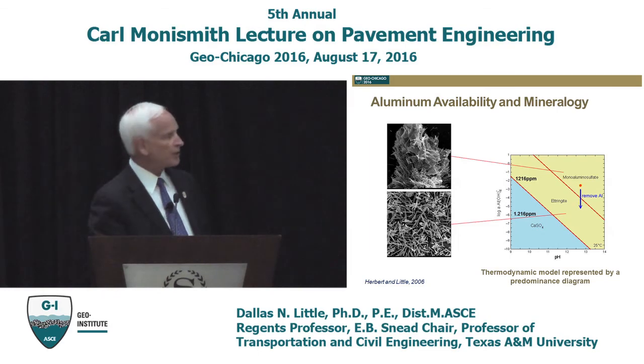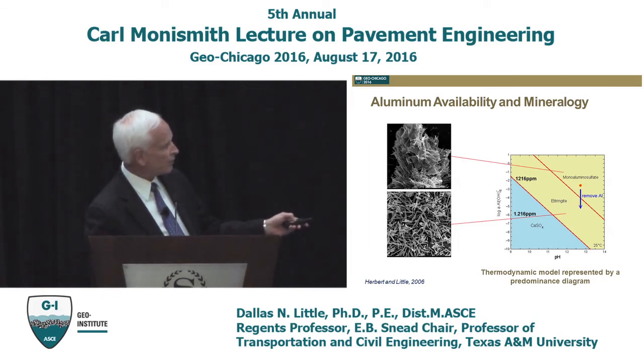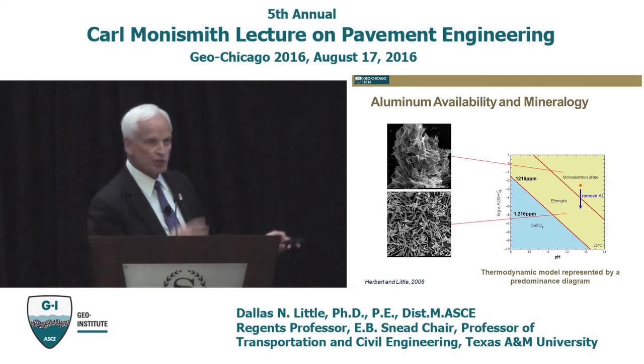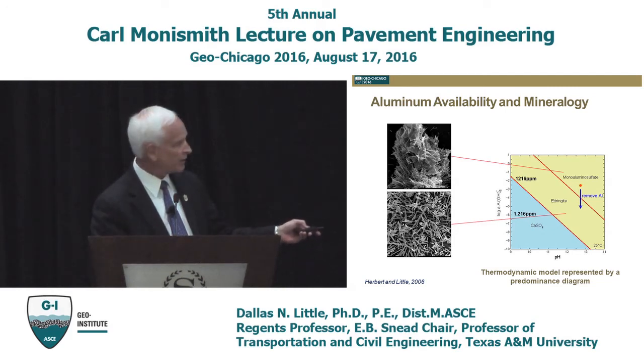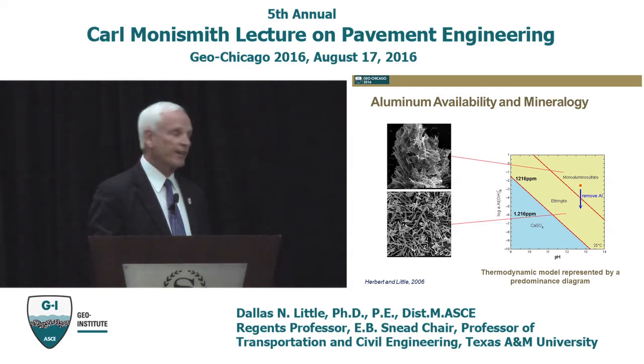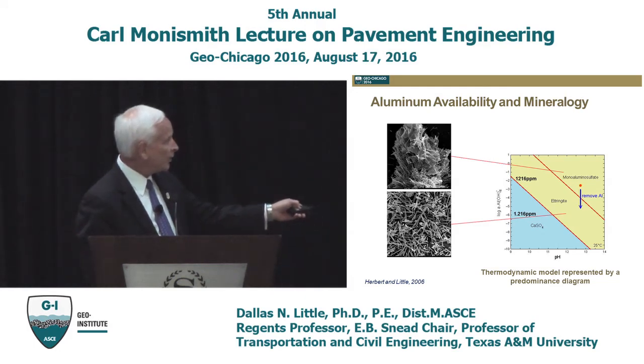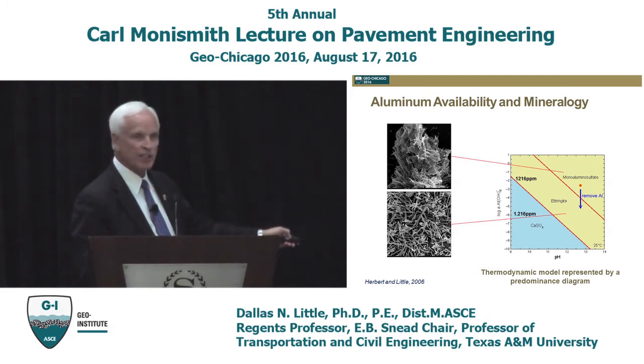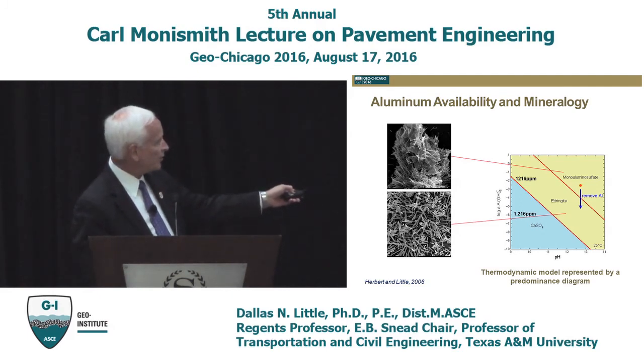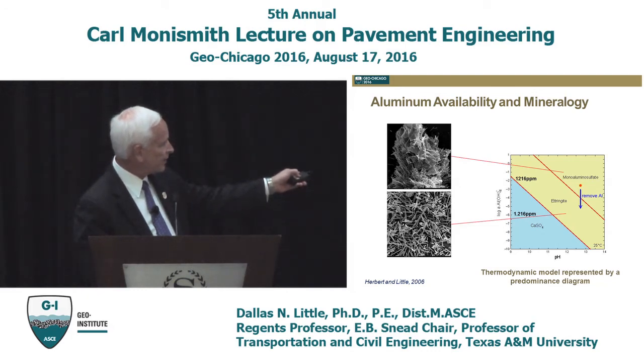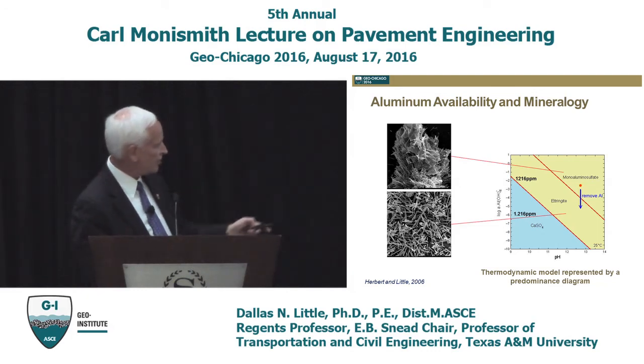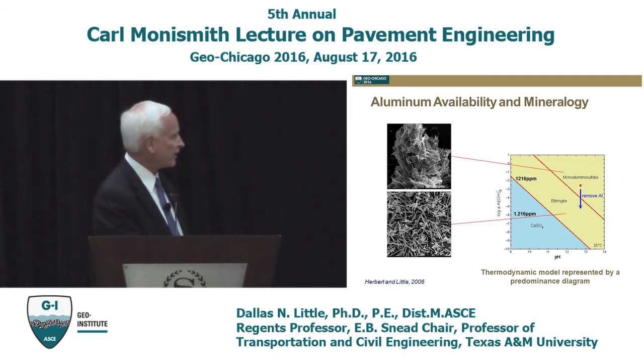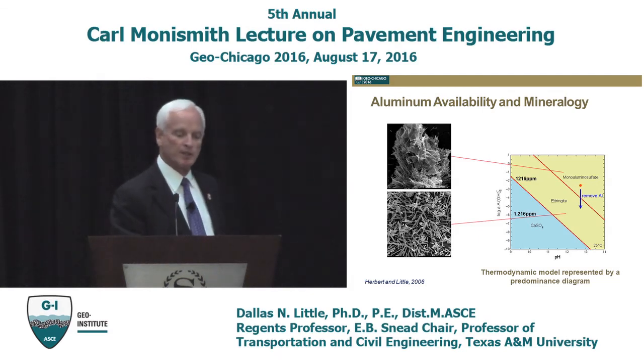So we said, well, what if you were to start with monosulfoaluminate and you took out the alumina, using some type of process, and I can't go into that right now, would it show up in the stability diagram? And of course it does. And we also saw it in the experiment. We started out with the monosulfoaluminate, which is up here in the upper left. Wish this thing worked. And then down here is the ettringite. So once we captured the alumina, we actually saw the transition in the micrograph.